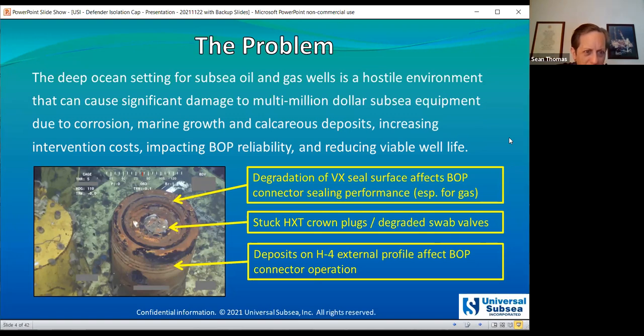You can see a cap to the left of the mandrel. There was a cap installed over the life of the tree, and irrespective of that cap, there was heavy degradation of the subsea tree mandrel, what we refer to as the subsea well interface. The sealing profile has heavy buildups. The H4 external connector profile also has heavy calcareous deposits, and the crown plugs are just a mess of debris piled up on top of them. So we can expect that the crown plugs would be difficult to remove, require a lot of cleaning initially, and then relatively high extraction forces. Similarly, for vertical trees, we generally expect that over the life of the tree, the performance of the swab valves will degrade significantly, especially for pressure testing performance.